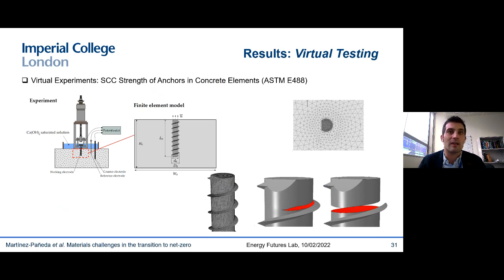And we can do anything. This is, for example, a very classic and complicated benchmark or standardized test to measure the susceptibility of screws, anchors, and bolts, which are typically very susceptible to hydrogen embrittlement because they're used with high strength alloys. And you can see that it involves steel into concrete beam material, but still there's no problem for these models.